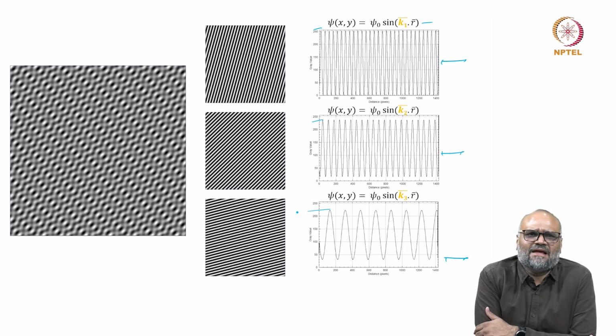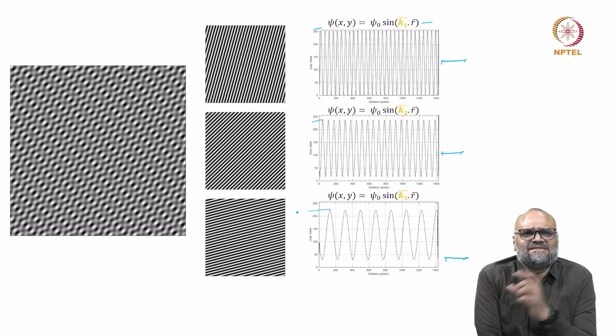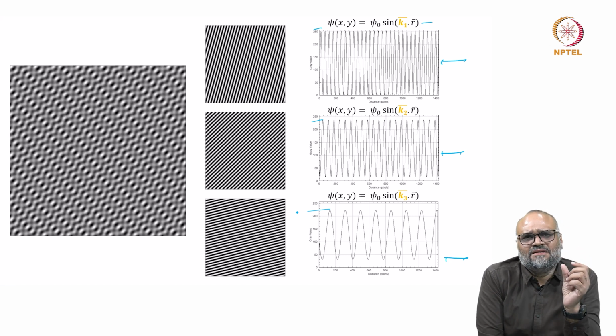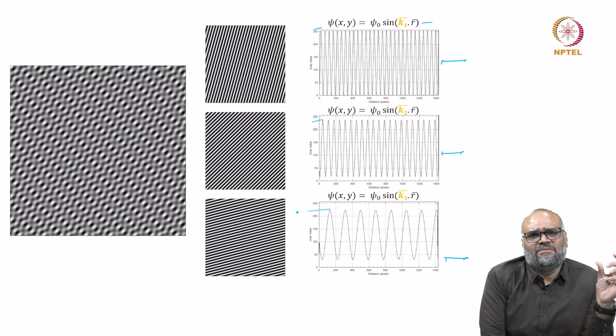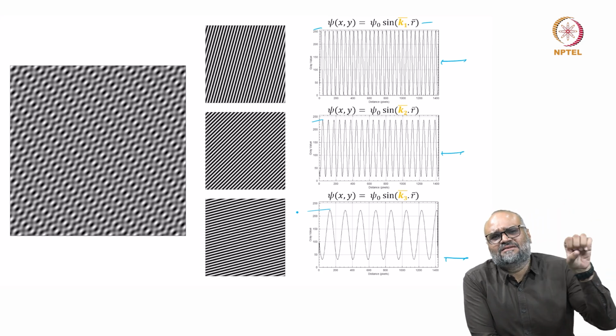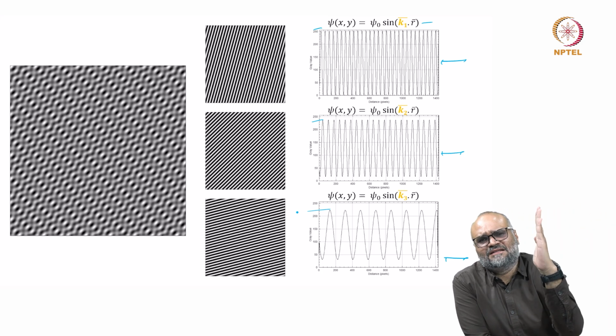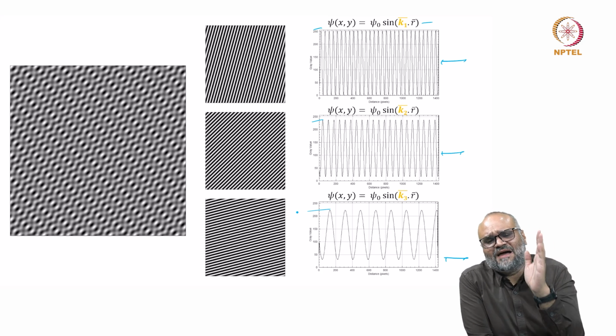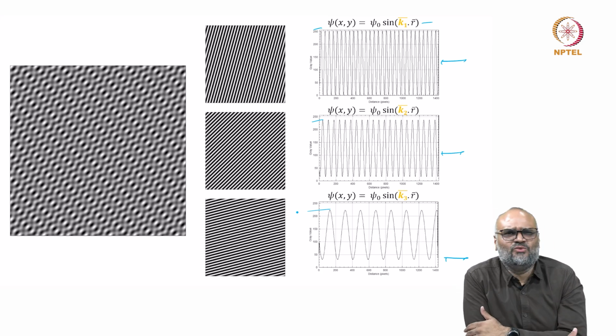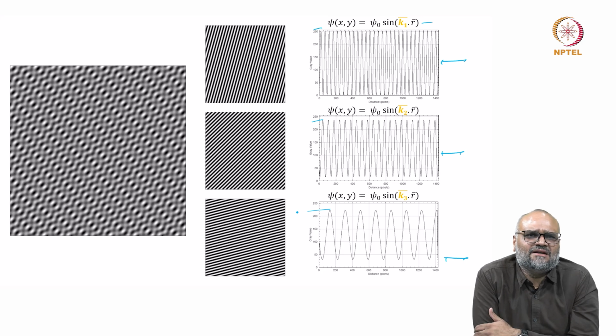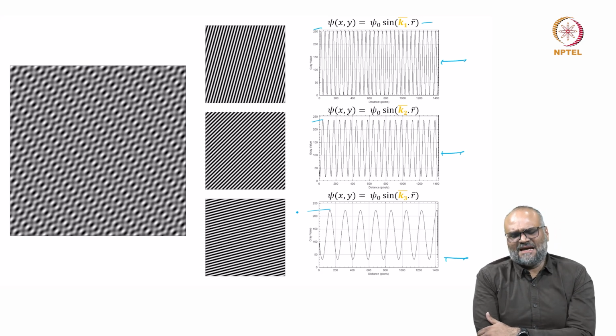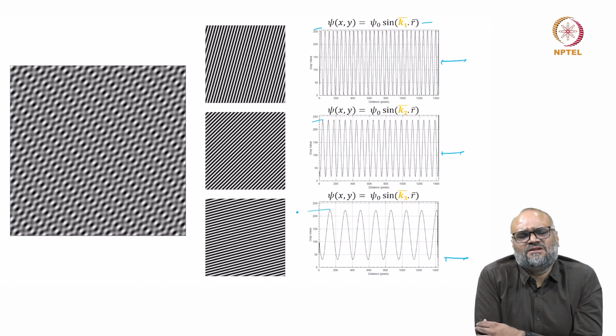So essentially, I can look at a microscope or a lens as a simple mathematical operator which is modulating my electron wave function, which is entering the specimen. The specimen itself acts as another modulator, and within an electron microscope, I'm trying to look at a convolution of various modulators or operators that exist, and I form an image. With this, I think I've shown you what the function of a lens is.